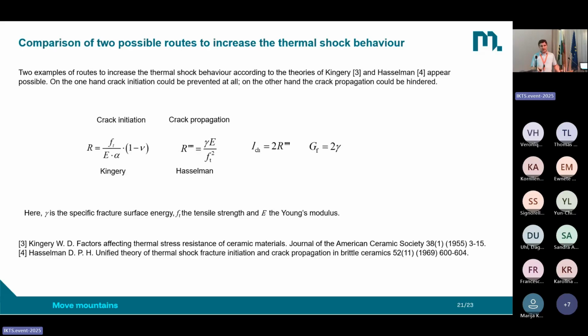Hasselmann did a different thing, and to make the explanation short, I show you this one. We have the characteristic length we have discussed before, and this is equal 2 times this Hasselmann parameter. So he made, as we discussed before, a balance between the energies. So Kingery said, okay, strain balance, and Hasselmann said energy balance. And what does it mean then? In this case, we have the resistance against crack propagation from Hasselmann, and Kingery says, okay, we have the resistance against crack initiation. And these are two completely different things.